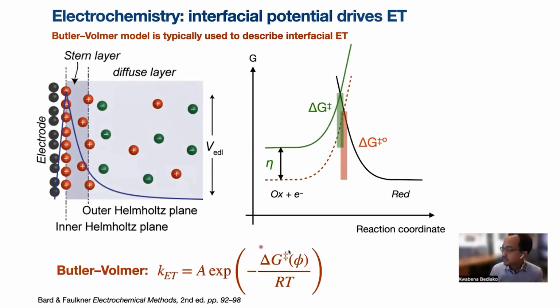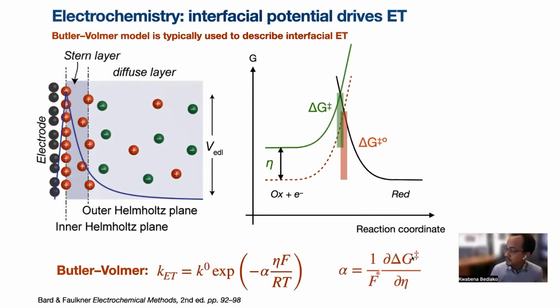And so as you apply a large overpotential, a potential in excess of the thermodynamic potential, this increase in overpotential is serving to decrease this delta G double dagger. And so then it is assumed that this delta G double dagger is changed as a constant fraction of the applied overpotential in the Butler-Volmer reaction through this transfer coefficient. And this model is really useful. It works in many cases, but it's quite limited in explaining certain asymmetries in some electrochemical responses or Tafel responses.